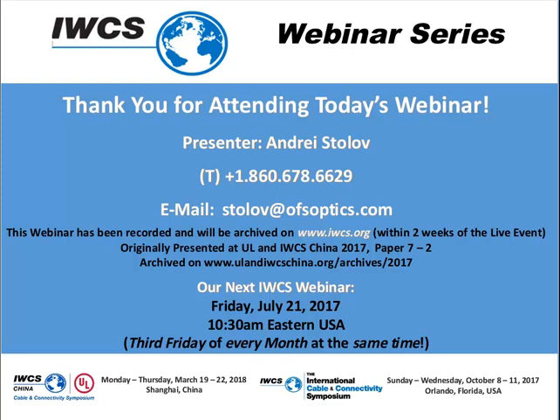But also, we can say, okay, everything depends on the specific application. There may be some application where even a fiber without a coating can be used continuously for 20 years if we do not touch this fiber, for instance. Anyway, if we have an honest comparison between different manufacturers of optical fibers, we should say if it is an acrylate coating, most likely it can be continuously, 20 years used up to 130 degrees C and not higher. Okay. Thank you.